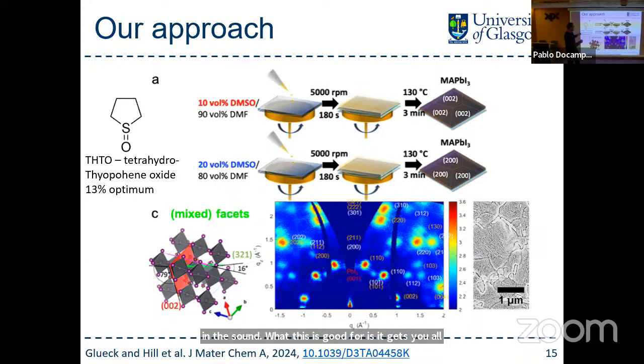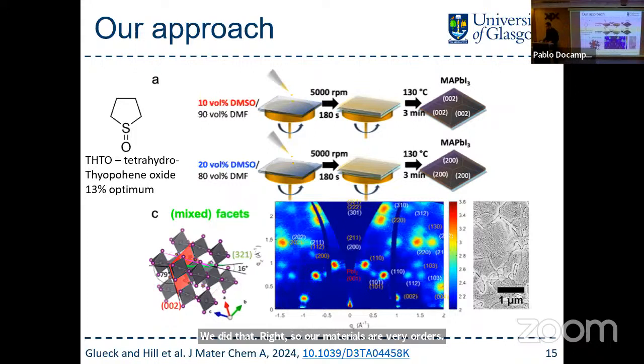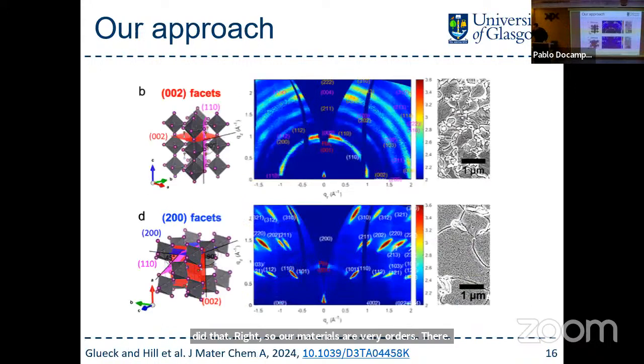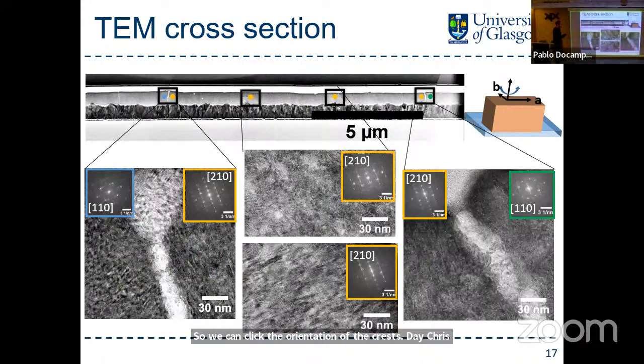If you were to put in a polycrystalline film, you would normally see a ring, because you collect from all orientations equally. Now, using this approach where we go to this intermediate phase with directed growth and then crystallize it out, we end up with spots. That is more or less what you'd get with a silicon wafer, right? So our materials are very ordered. They're not single crystal, but they're very large, and we show that we can tweak the orientation of the crystals from lying flat to vertical. The crystals are very large. You can get up to 30 microns, and it is a single crystal all the way through.